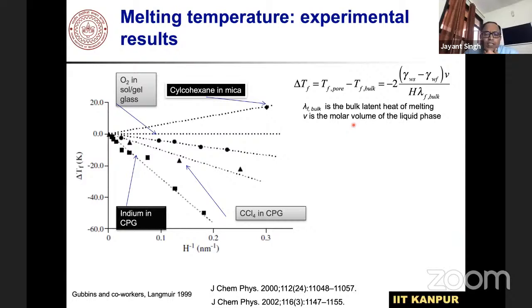There's another example which we were very excited about, on the shift in the freezing point of fluids in confinement. This expression is available in any chemical engineering book. It describes the shift in the freezing point. This is the freezing temperature of the fluid in the bulk, and this is the freezing temperature of the fluid in the pore, and this is connected to the interfacial tensions, the pore width of the system, and the latent enthalpy. So it tells you that this is linear in nature if you have this information on interfacial tension.